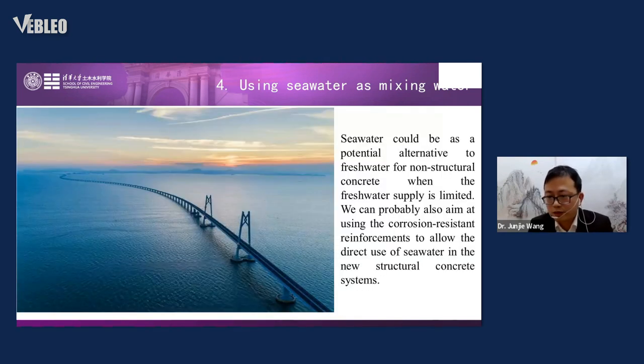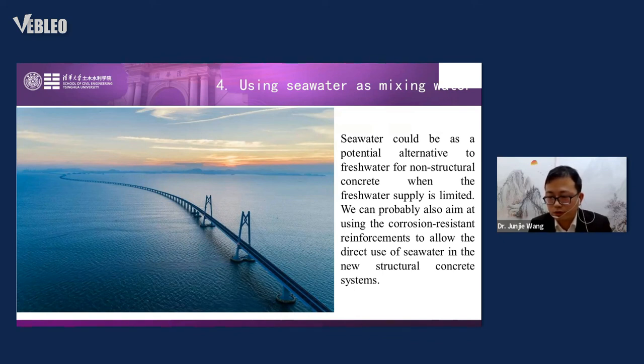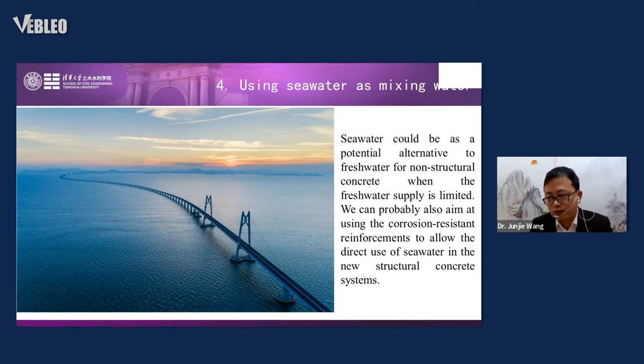In conclusion, seawater could be a potential alternative to fresh water for non-structural concrete. When fresh water supply is limited, we can also aim to use corrosion-resistant reinforcement for direct use of seawater in new structural concrete. When the concrete has no reinforcement required, or we use corrosion-resistant reinforcements, we can use seawater — it gives better compressive strength and much less shrinkage.